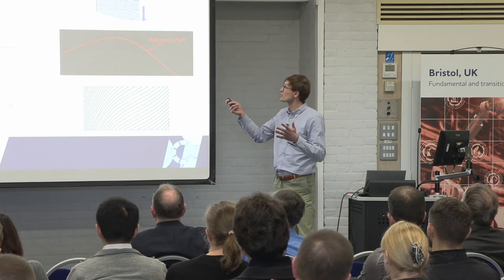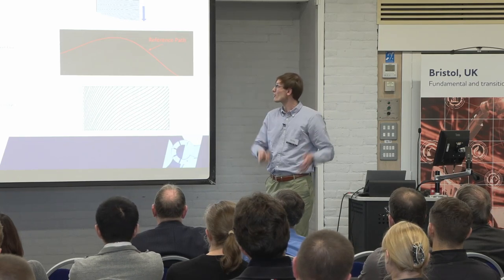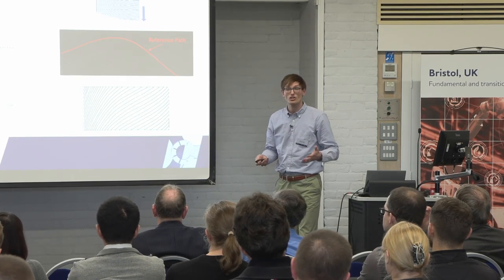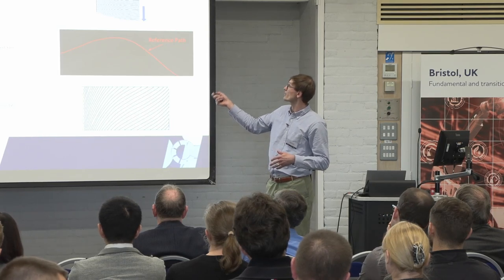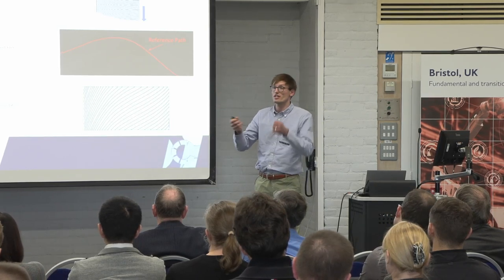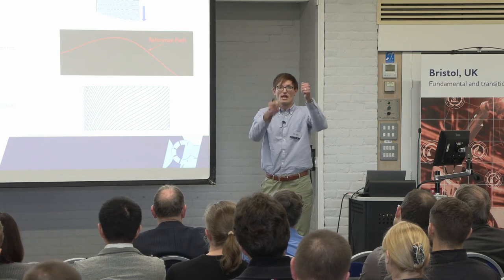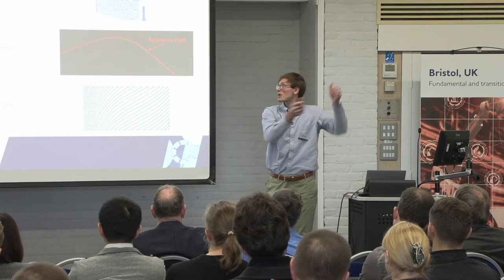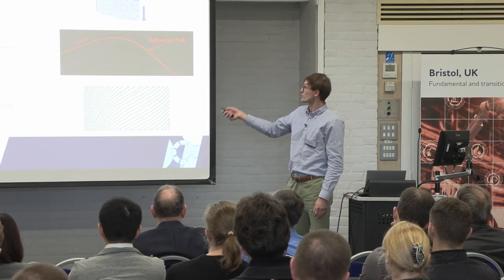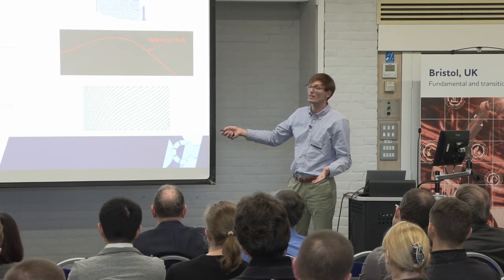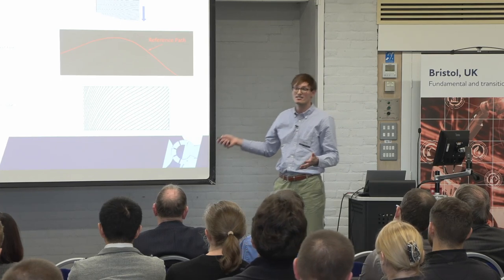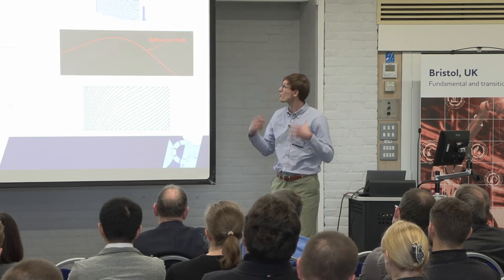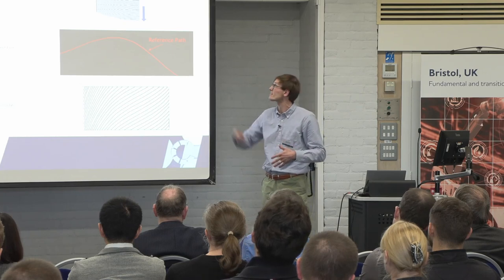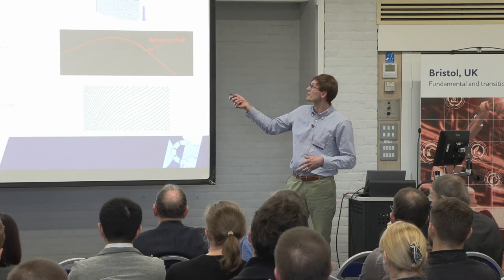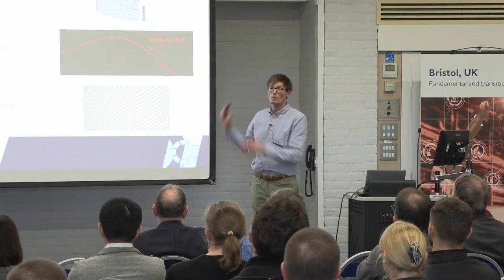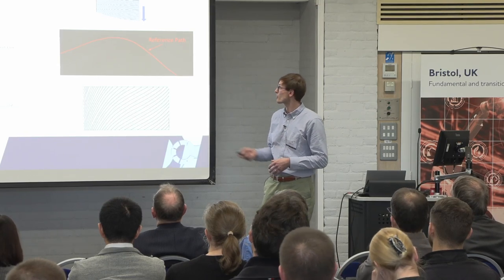And so at the University of Bristol, Eric Kim and others developed the continuous tow shearing process, which essentially steers by shearing a tow continuously. So you can think of that as just grabbing a tow and continuously shearing it bit by bit to then steer a reference path. And the advantage of this is that you completely eliminate these defects, and you can also tessellate individual tows. And this process, originally termed continuous tow shearing, is now being commercialized by ICOMAT as rapid tow shearing, and this is what we then used in this European Space Agency project.